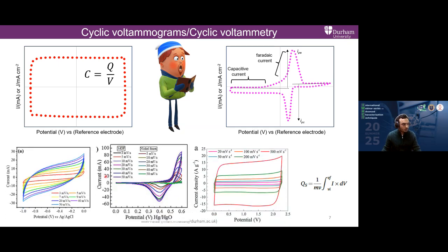So this is a very basic example of activated carbon, which is tested at several scan rates, and the reference electrode used is Ag/AgCl, and you can see the potential ranges from -1 to 0.0 volt.